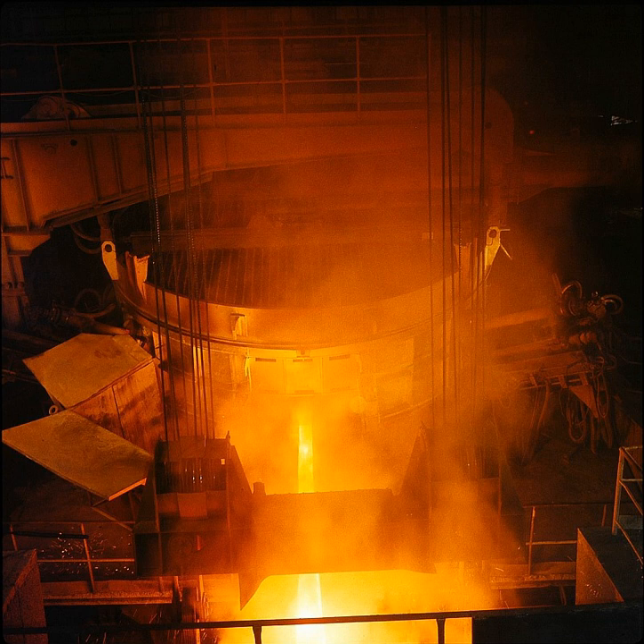The scrap is loaded into large buckets called baskets, with clamshell doors for a base. Care is taken to layer the scrap in the basket to ensure good furnace operation. Heavy melt is placed on top of a light layer of protective shred, on top of which is placed more shred.